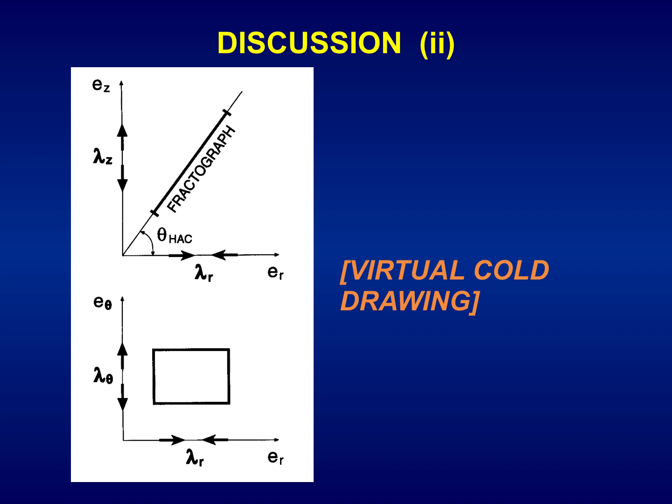This is the schematics of this virtual cold drawing in the direction of the fractograph. Then, with computer-assisted analysis, we take a real fractograph of a steel 3 after 3 cold drawing passes, 3 steps of cold drawing, 3 passes through the dies, number 3, and this is the enlarged fractograph of a hot rolled material, steel 0. This is a virtually obtained number 3 coming from a 0 level of cold drawing.